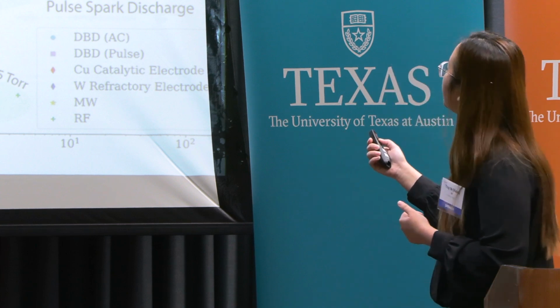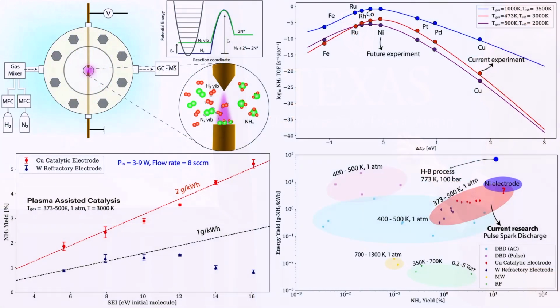And as we can see here with the red and purple curve, if we don't change the gas temperature much, but increase the vibrational excitations of the nitrogen molecule, we can definitely enhance the production rate for ammonia. So our research right now initially starts with copper, which is a common electrode, but moving forward, we will investigate nickel, which is showing significant ammonia production here.